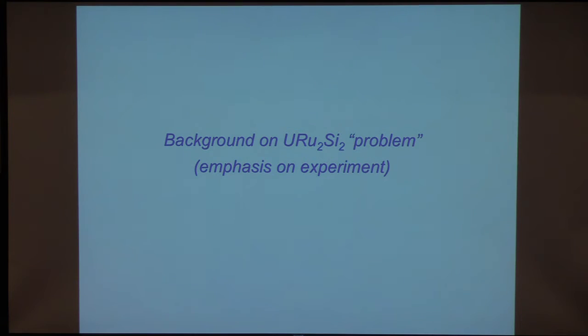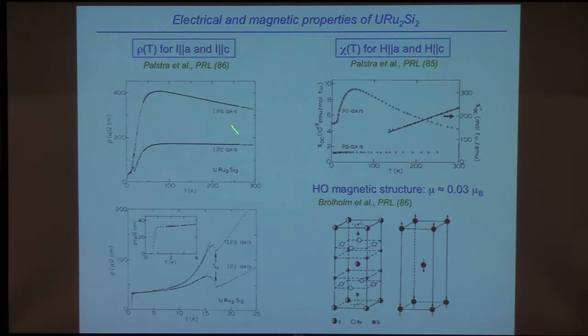So now I want to go back to uranium ruthenium-2 silicon-2. You'll see some similarities. So here is some early work back in 1986. There were 3 groups that reported on this at intervals of 1 month in the literature. And the group that discovered it was Schlabitz and co-workers in Cologne. And then John Mydosh's group worked on it, and our group worked on it. And we had papers published at about the same time. But this is from John Mydosh's group, and this is resistivity versus temperature.